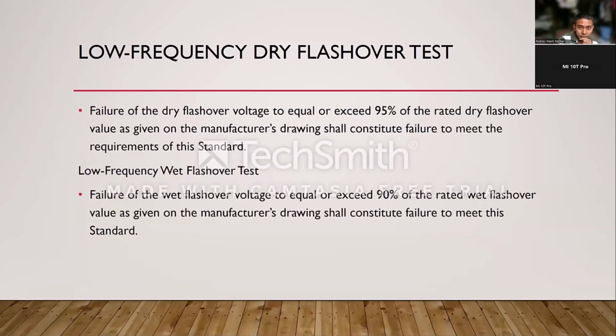Low frequency dry flashover test. The failure of the dry flashover is equal to 95%. So, ganun kataas siya, rated dry flashover, given on the manufacturer's drawing, constitute failure to meet the requirements of this standard. The low frequency wet flashover test naman is equal to or exceed 90% of the rated wet flashover, as given on the manufacturer's drawing, constitute failure to meet this standard.